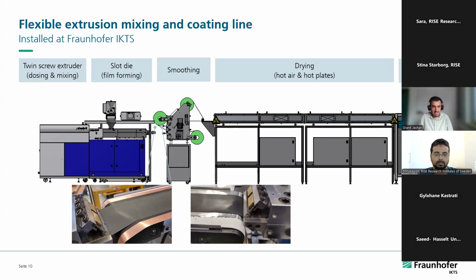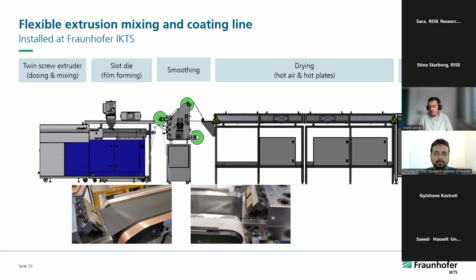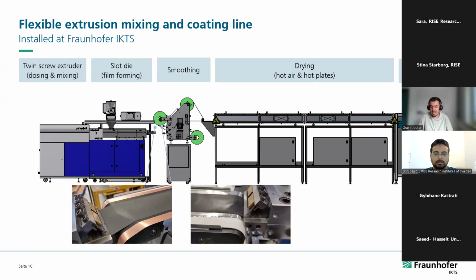About each step: for the twin screw extruder we are using, there are different possibilities for dosing the active material, the binder, and the solvent. Through the whole twin screw, there are 4 positions where you can dose: in the first position just the powders, and in the second position the binder. This can be optimized depending on the chemistry you are using and the process you want to develop.